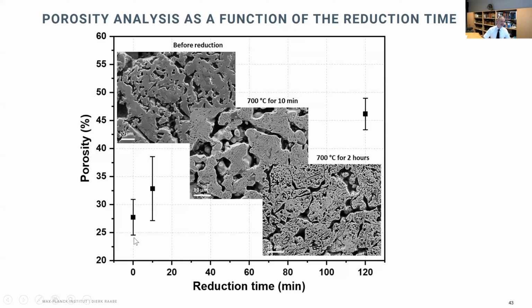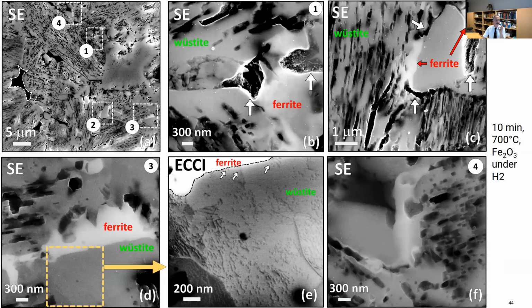And this is, for instance, analysis that Jan Ma, my colleague, made regarding the evolution of the nanoporosity as a function of the reduction time, to really understand where is the free volume, where can the water recombine, where can it form, where is it maybe recondensing, or do you maybe form water bubbles that lead to fracture and so on. There are many questions that are totally unclear. Where is actually the oxygen going to? How is the hydrogen penetrating a certain bulk oxide and so on? This is just a very messy slide.